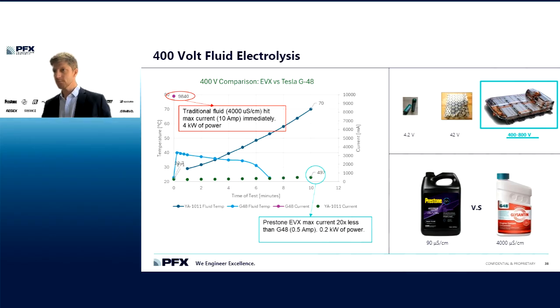So if we want to look at the data for what we just watched, right, we saw bubbling between 2 electrodes. What does that really mean? So this dark blue line on the graph here shows the temperature profile. So we start around 25 degrees Celsius, and this increases to 70 degrees Celsius at the end of 10 minutes. So this test lasted 10 minutes. We did see an increase in temperature, but we're still well within the safe range for battery thermal runaway.